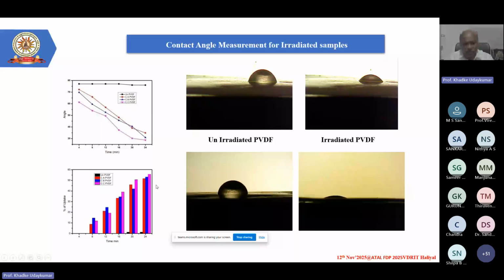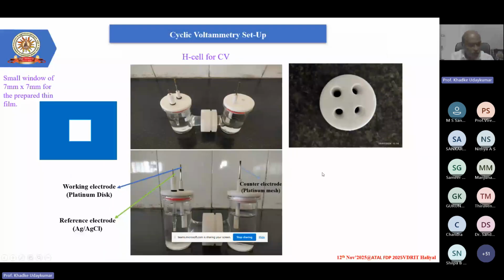These are the H-cell developed in my lab, and using this H-cell we could find out the capacitance voltage value in order to understand the charging and discharging of the battery. We observed that for a longer duration, the charging value achieves the same value, and the discharging value also achieves the same value. There is no degradation happening. So that helps us to say that yes, the dendrite problem has been solved because of the uniform distribution of the porosity that has been created.